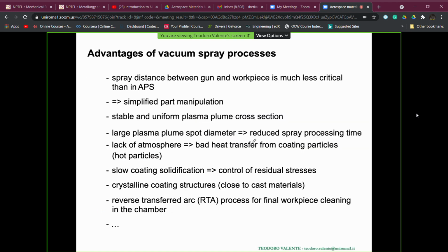The vacuum plasma spray process has some advantages with respect to the standard air plasma spray process, but obviously it is more costly because we need a chamber and we need all the pumping unit, we need all the pressure controls. Then we could be limited in terms of size of the component to be coated by the chamber dimensions.